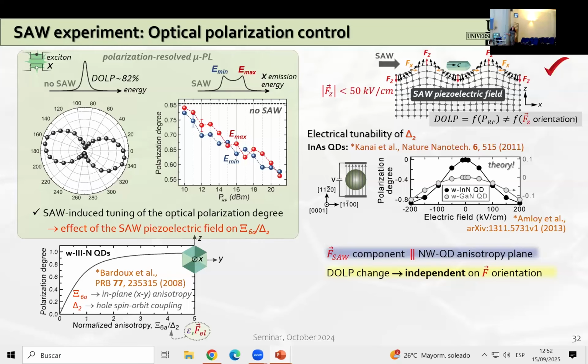And the underlying mechanism is that the piezoelectric field is tuning the spin orbit energy and thereby affecting the polarization degree. This tunability of the spin orbit coupling by an externally applied electric field was previously seen in other quantum dot systems, such as indium arsenide. This was an experimental observation. And it was also theoretically predicted for wurtzite nitride quantum dots, where it has been shown that by applying a static electric field up to some 200 kilovolts per centimeter, we can indeed obtain such a change in the polarization degree between 0 and 80% of the emitted photons.